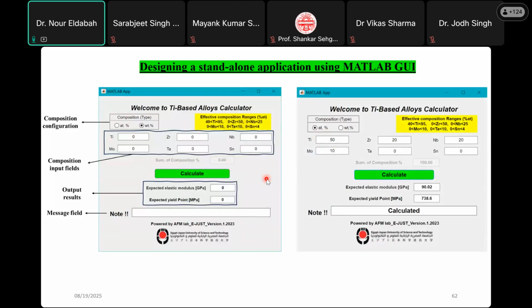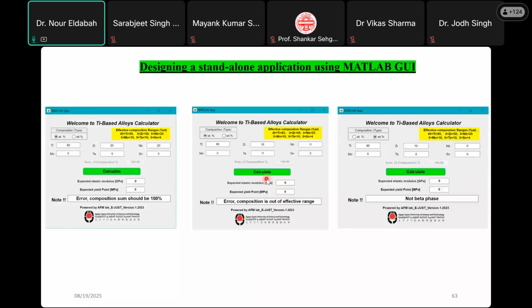But with this tool, you can just go to the standalone application and make your calculation, predict the expected elastic modulus and yield point, and modify your design until you reach the optimum 2 or 3 compositions and make them in one run, reducing the time needed for testing and characterization, because you are working toward the effective point you need. Also, this software can detect if you put a composition lower or more than 100, or if it is out of the effective range, or if it is not a beta phase, because I stated previously that if the alpha phase exists, or an alpha-beta composition, the neural network will not work effectively, and the error will be very high in this case.